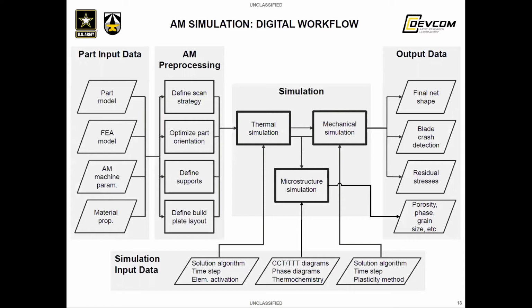Coupled to this thermal solution is the mechanical solution, which takes those temperatures as an input and calculates the stresses and strains that are caused by the severe thermal gradients that are often present in laser powder bed fusion and other additive manufacturing methods. The goal of mechanical simulations is to calculate those residual stresses because they are an ever-present challenge in various forms of additive manufacturing, causing things like the collision of the powder blade recoater with the part because it's too warped, or a failure to actually reach the tolerances required of the manufactured part.